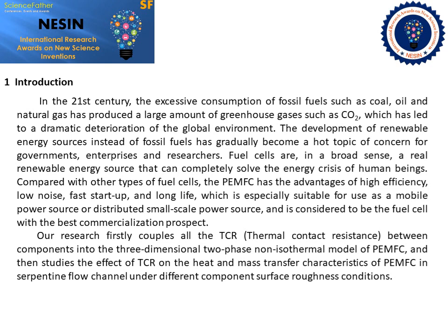Our research firstly incorporates all the thermal contact resistance between components into the three-dimensional two-phase non-isothermal model of PEMFC, and then studies the effect of TCR on the heat and mass transfer characteristics of PEMFC in a serpentine flow channel and different component surface roughness conditions.